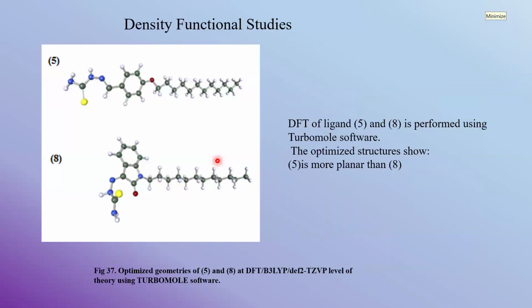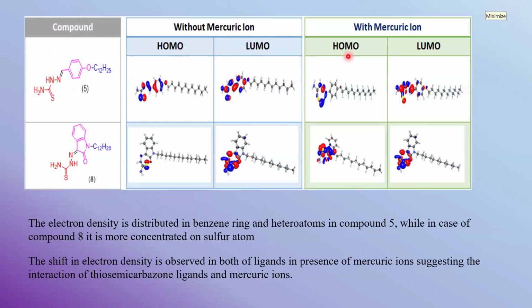We also performed some functional studies. This is the optimized geometries of the two ligands. This is the linear molecule. This one is not as linear because we have a cyclic ring here and other groups. So these are the HOMO-LUMO calculations, electron density distributions without mercuric ions and with mercury ions for the two ligands. For the HOMO, you see the electron density is located here in this case, while in this case it is located here with the sulfur and nitrogen.